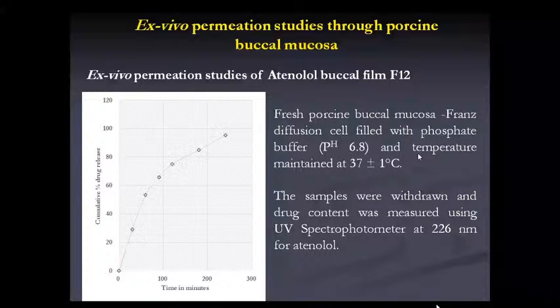If you look here, this ex vivo permeation will also be done with the help of porcine buccal mucosa using the Franz diffusion cell. Usually there will be a donor and a receptor compartment, and the film attached to the porcine buccal mucosa will be clamped between the donor and the receptor compartment. From the receptor compartment, the sample will be taken and analyzed using a UV-visible spectrometer at 226 nanometer for atenolol, so that you can calculate your drug release by comparing with the standard curve of atenolol.